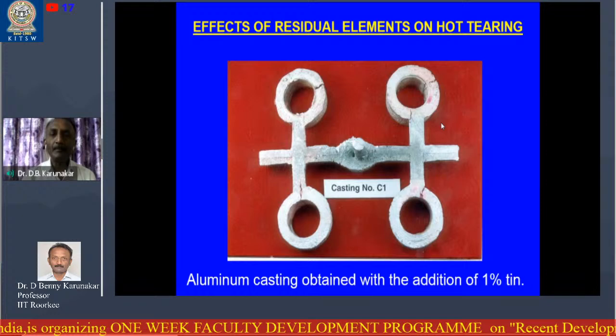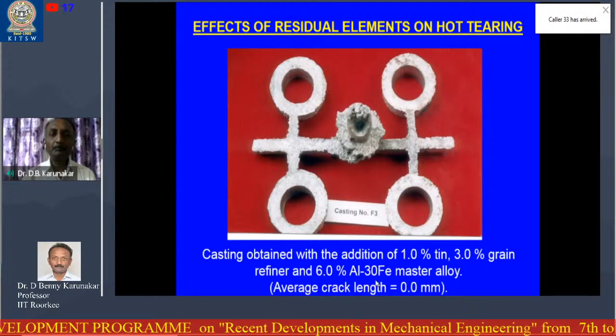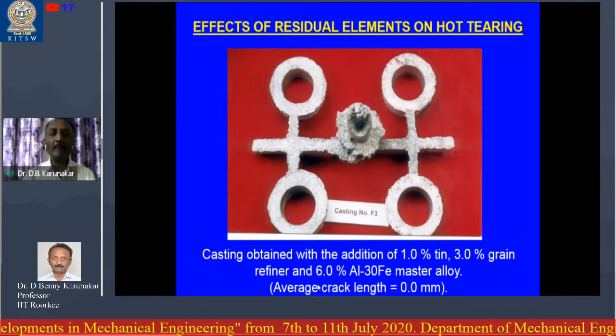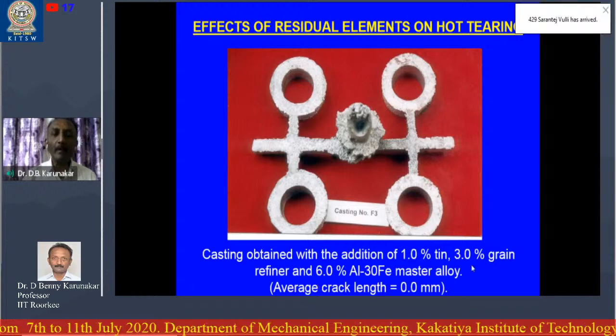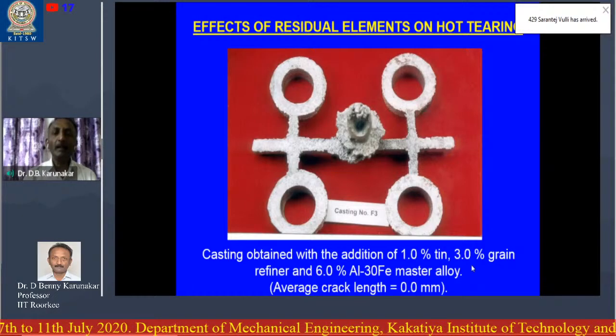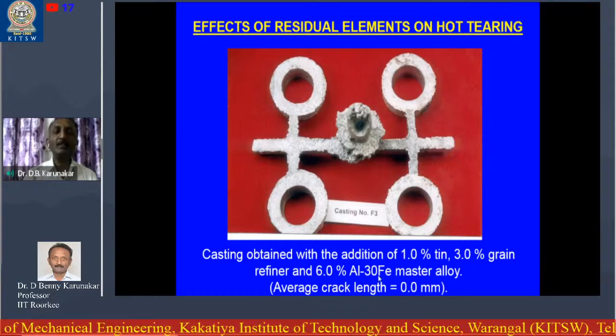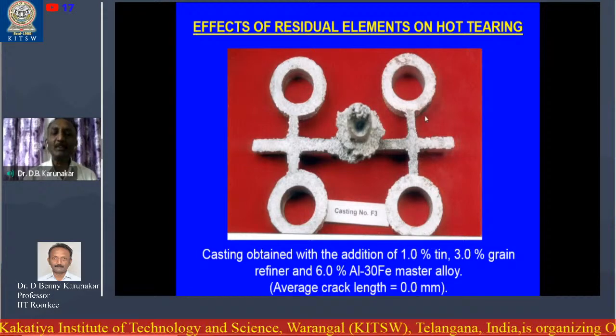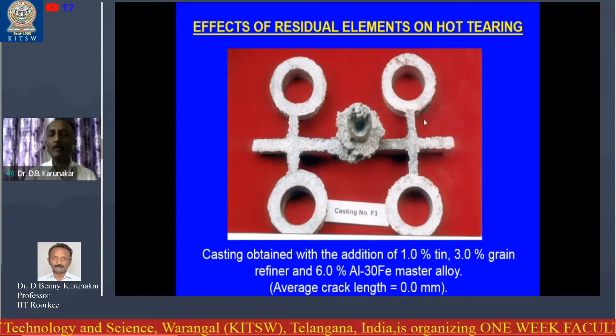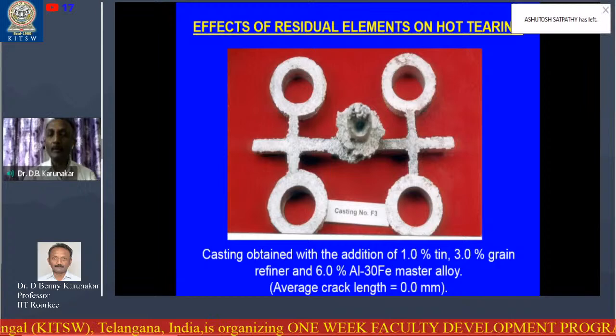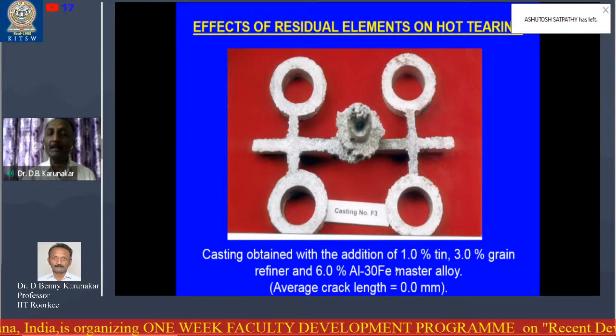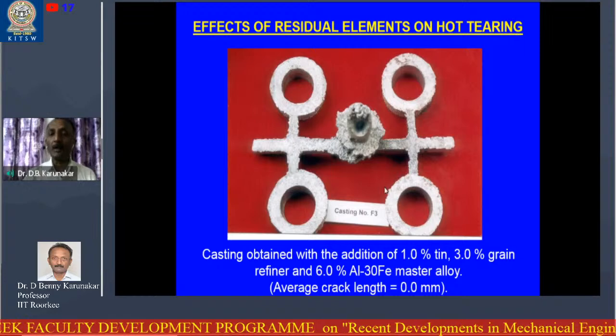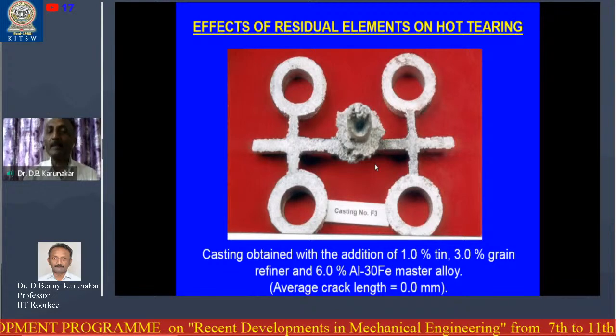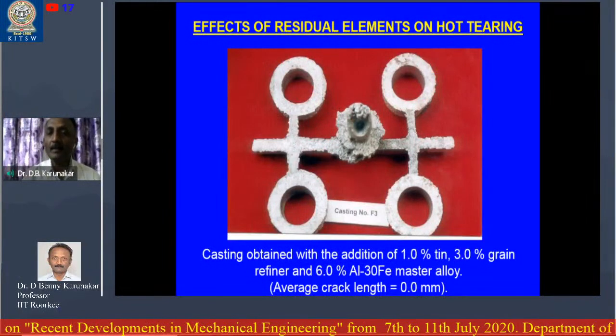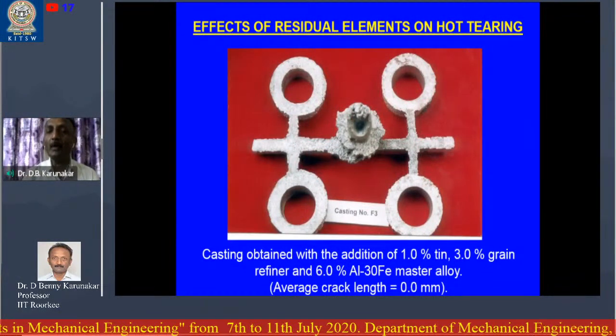Later, we added iron. Initially we made an Al-30Fe master alloy, and out of that we added 6% of this iron master alloy to the casting, meaning to the 1% aluminum, 1% tin mix. This iron helped us prevent the hot tearing. Then we started investigating how the addition of iron helps reduce or prevent hot tearing.